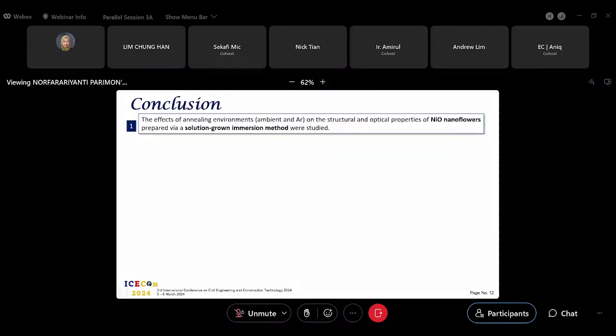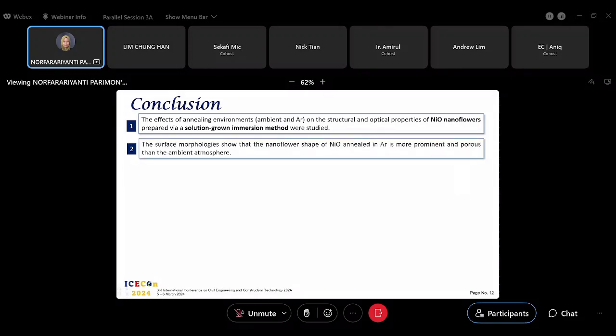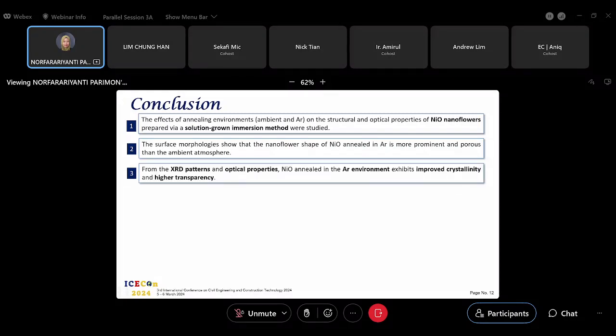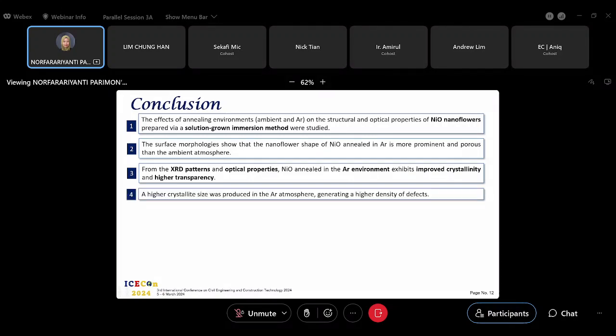For the conclusion, we successfully deposited nickel oxide nanoflowers using the immersion method, and then we studied the annealing environment between ambient and argon. We can see the surface morphology of argon is more prominent and porous than the ambient atmosphere. From the XRD and optical properties, nickel oxide annealed in the argon environment exhibits improved crystallinity and higher transparency. A higher crystallite size was produced in the argon atmosphere, while generating a higher density of defects.